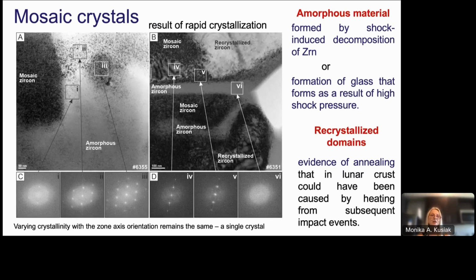And the last example is the mosaic crystal. I chose the most complicated example to show you, to see how interesting it is, because the various crystallinity is with the same zone axis orientation. So we have various crystallinity, but the same orientation, which means we deal here with a single crystal. And take a look, starting from the center, number 4 here. We have the very sharp diffraction spots of the mosaic part of zircon, and they have the same orientation.